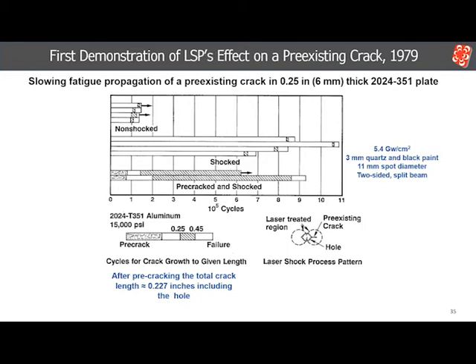In the other set of tests, the specimen was first fatigued a short time to initiate a short crack about 0.9 of a millimeter long, emanating from each notch. Then the tips of the cracks were laser shocked on each side of the hole, as shown in the illustration. Before testing, the crack lengths were nominally about 5.7 millimeters long, including the hole and notches.